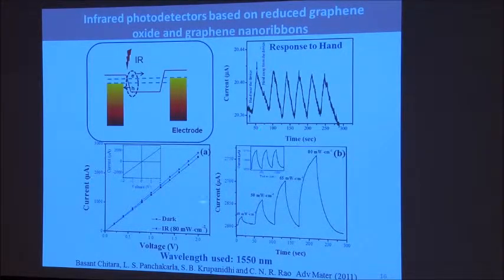You can see the infrared light when you put a radiation infrared laser on it, you get wonderful signals. In fact, I have shown here, when you just put your hand in front of this graphene detector, you can see the presence of the hand, or when you remove the hand, you can see the signal. A very, very sensitive infrared detector is what you can make with graphene.